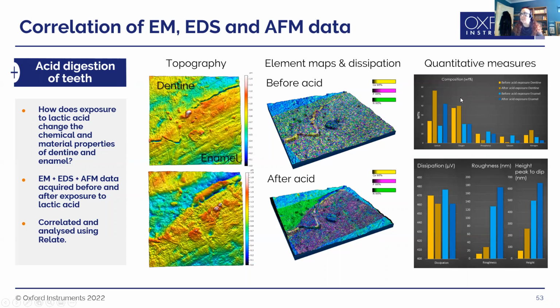And here you can see in the gold colours, this is the dentine, and in the blue, this is the enamel layers. And you've got the before and after next to each other. So you can see there's been quite a big change, not so much in the oxygen, but in the carbon, phosphorus, calcium, and in the nitrogen signals as well. And this correlated with some of the dissipation changes we were observing.